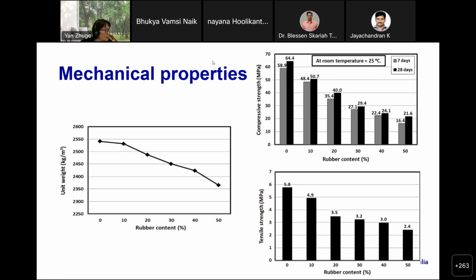Okay. So this diagram shows us the change of the unit weight. You can see when you increase rubber content up to about 50%, there is a reduction of the density of concrete. So you can make reinforced concrete materials that are actually lighter when you use more crumb rubber. So this is one of the advantages of using crumb rubber in concrete.